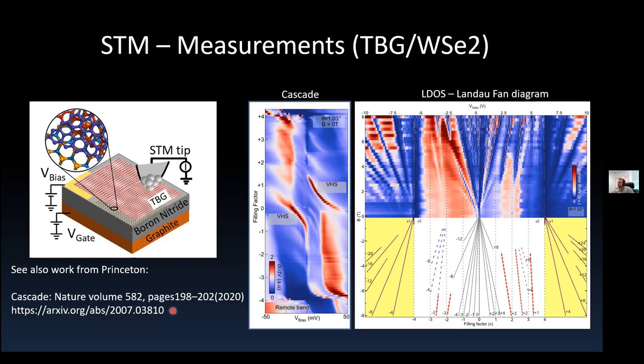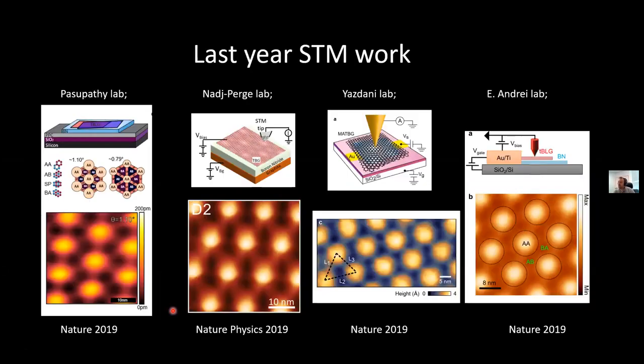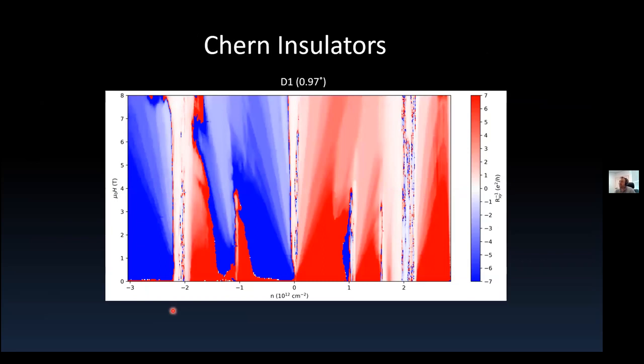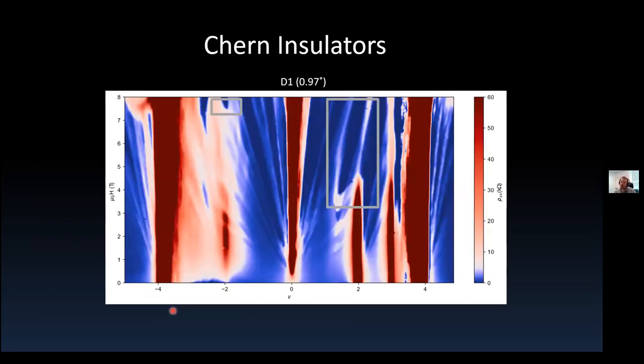One of the good things is that these local measurements match relatively well with all these transport measurements, but moreover they show you that the phenomenology of these systems doesn't change dramatically if you put them on a different substrate. But it seems that, at least from all these experiments, the tungsten selenide substantially improves the quality of our devices. And with this, I want to stop and open the session for questions. Thank you very much.